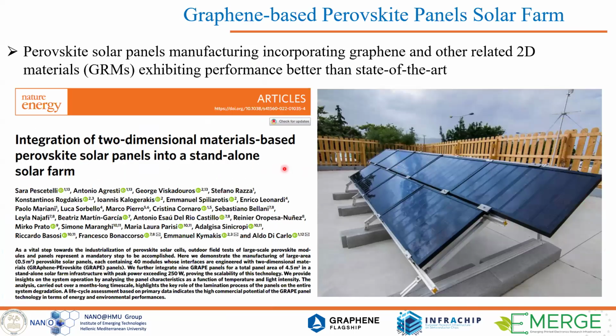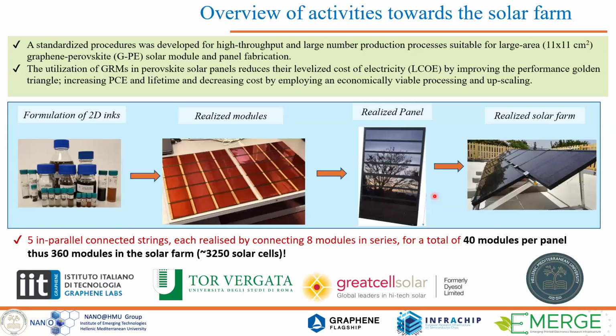This is the highlight of the group and of our participation in the Graphene Flagship: a publication in Nature Energy on the cover, a big collaboration between many partners of the Graphene Flagship. Here we demonstrate the first solar farm, as I told you, with quite good performance for at least 9 months, until lamination failure of the panels led to degradation of the PV panels' performance. In this very big effort, we and our colleagues formulated the materials, prepared the inks, and realized the cells and the modules. We speak about more than 3,000 solar cells integrated in 9 panels.